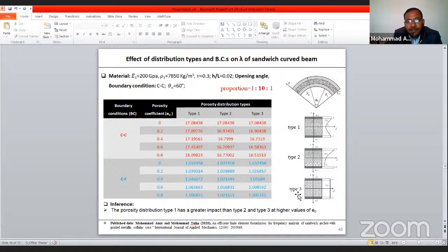Now, the effect of distribution types and boundary conditions is observed for this sandwich curved beam. Here we have considered two types of boundary conditions: clamped-free and fully clamped. By increasing the porosity coefficient e naught, these porosity distributions also affect the frequency response of the structure. Let's say on increasing the porosity coefficient for type 1, it is increasing, but for type 2 and type 3, the frequency parameter is decreasing for both clamped-free (cantilever) and fully clamped beams.